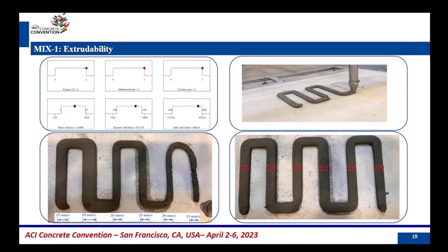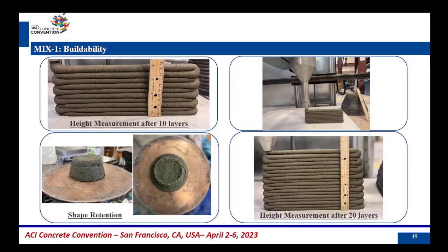For the extrudability evaluation, we printed a filament with different printing speeds, starting from 15 millimeter per second to 35 millimeter per second, to get an optimized printing speed that gives a good extrudability. The optimized printing speed in this case was 15 millimeter per second, and we got good extrudability in terms of dimension consistency, conformity, and also the surface quality, as you can see, is very good.